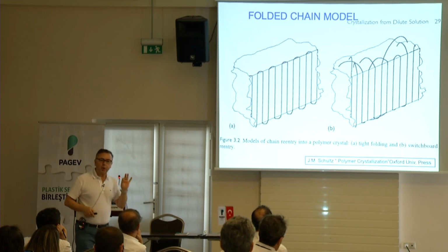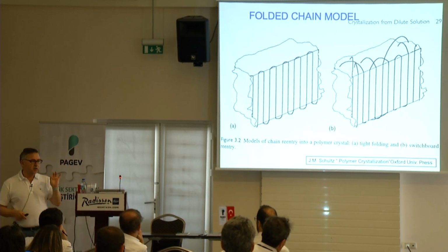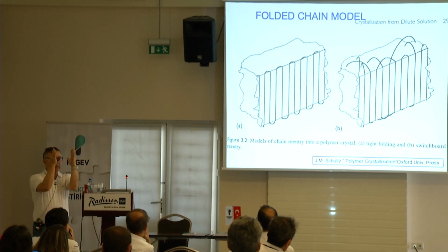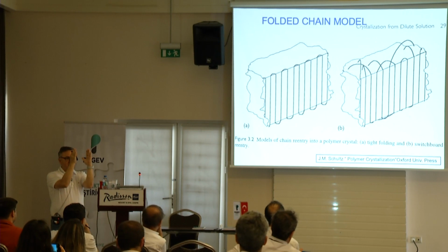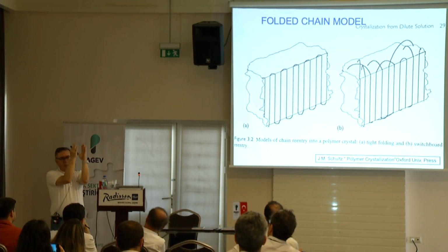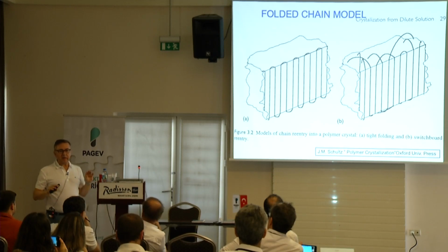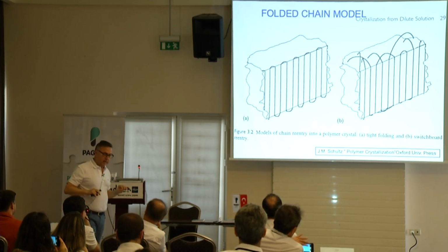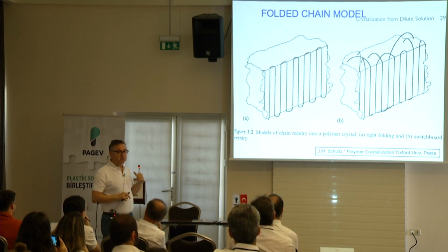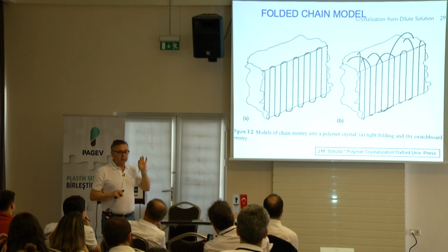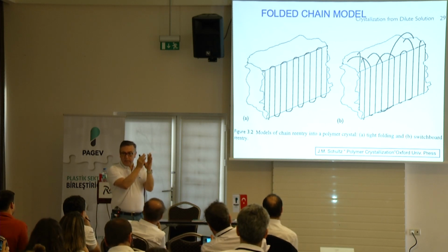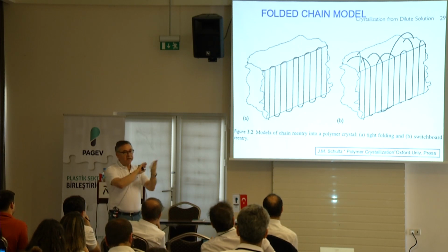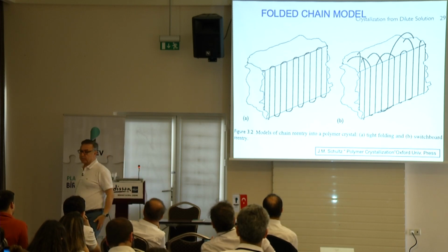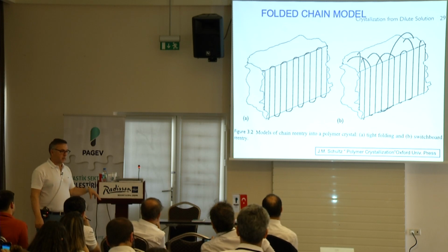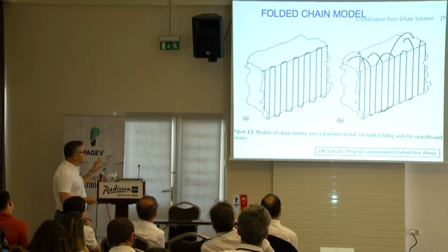But still, the key point of polymer crystallization, just to take away from this slide, is that they have to become parallel. Polymers cannot crystallize when you're doing this. They have to become parallel. And this is an important one when you are doing processing, where you're making fibers, films, bottles, injection molding. Processing is going to influence whether or not they're going to become parallel. Because if you do things that make them anti-parallel or prevent them from becoming parallel, you're basically preventing it from crystallizing, even though it has the ability to crystallize. That's the important takeaway from this.